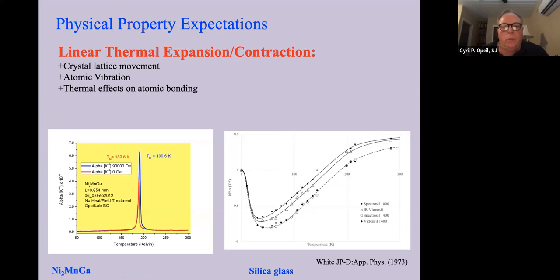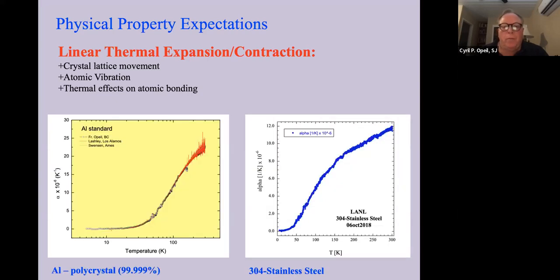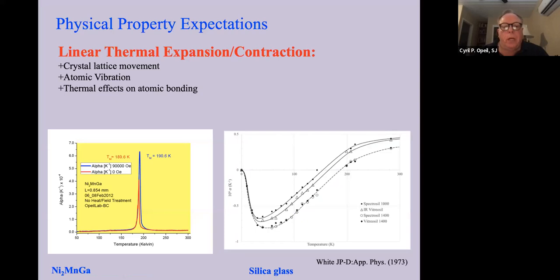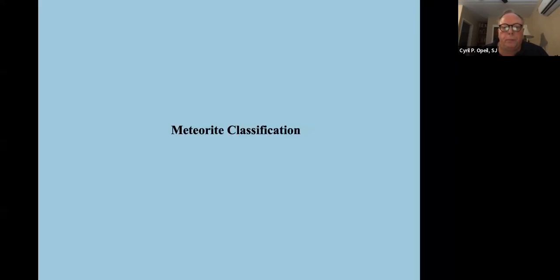Now, linear thermal expansion doesn't always have to be so well behaved like here. It can actually be a little bit different. Years ago, I measured nickel 2 manganese gallium, which has a major crystal transition in between at around 190 Kelvin. And that's actually what you see there. And so the alpha picks up. That's the expansion coefficient that you have. And on the right, we see a silica glass, where you have negative thermal expansion below basically 150 Kelvin for various silica glass. So these are the kind of things that you might see.